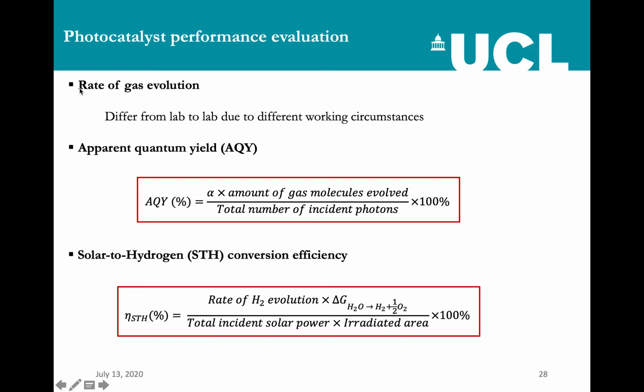So one cannot really say, let's say one group shows 100 micromolar per hour and another group says 500 micromolar per hour, that this 500 micromolar gas producing group can claim that they have the superior activity, because there might be these kinds of issues that we discussed before. So these two parameters, apparent quantum yield and solar to hydrogen conversion efficiency, are more reliable and accurate for evaluating the photocatalyst system.